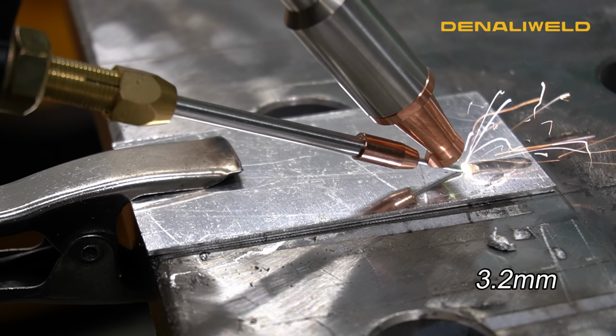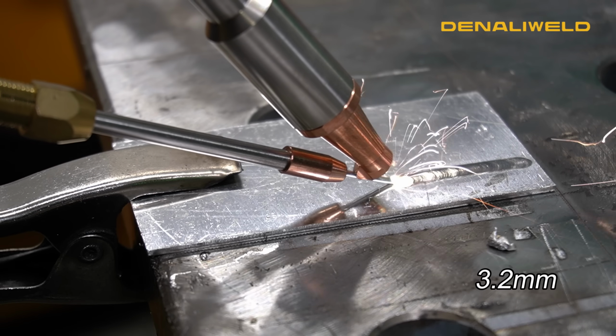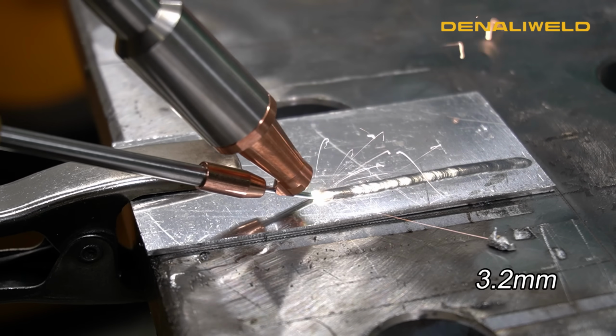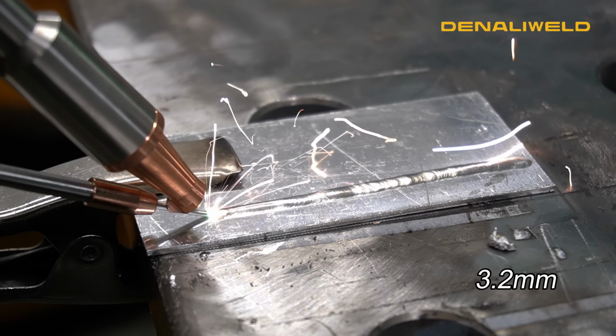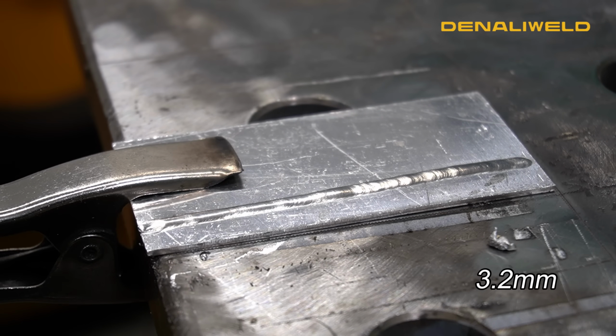So now we're set up with the proper wobble size for the 1/8 wire at 3.2 millimeters. As you can see, the profile of the weld is ideal matched with that wire size.